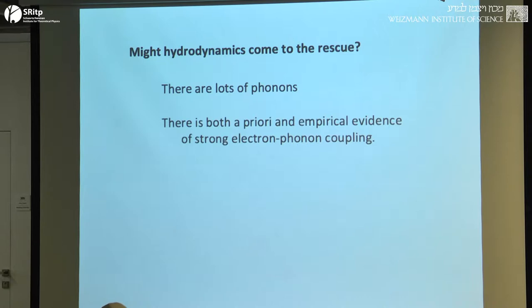And moreover, despite the fact that the optical phonons don't show up in the resistivity, there's all sorts of other evidence that the electron-phonon coupling in these systems is very strong. In fact, Mueller looked at the cuprates precisely because he thought there would be a very strong Jahn-Teller coupling to the phonons, and he thought that would be good for superconductivity. The perovskites are well known for their strong electron-phonon couplings. There's all sorts of evidence of charge ordering that has major effects on the phonon modes. As you dope the system, distances to apical oxygens change by really large amounts. There are really strong electron-phonon couplings here. Now, maybe we can get out of phonons by going into some sort of phonon drag regime, but with so many phonons with such complex dispersions, that's hard for me to imagine.